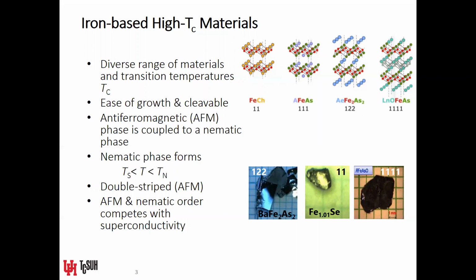Now the nematic phase, as I'll show you shortly, forms in between a structural phase transition and a magnetic phase transition. In this talk, I'm indicating T_S as the structural phase transition temperature and T_N as the Néel temperature, or basically the magnetic phase transition temperature. So you can see a nematic phase forming in between these two very important temperatures. And that nematic phase not only manifests a crystal symmetry breaking, but it also manifests an anisotropy in the resistivity, if you take such a measurement. So there is an electronic nematicity that is associated with this structural nematic phase.